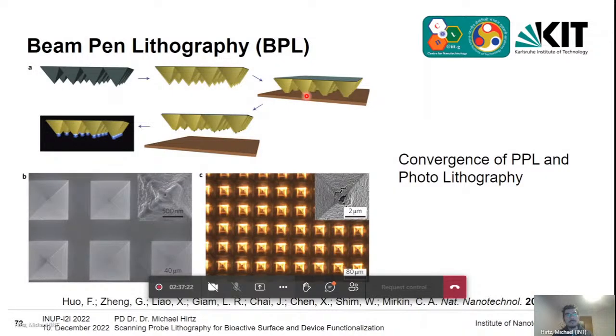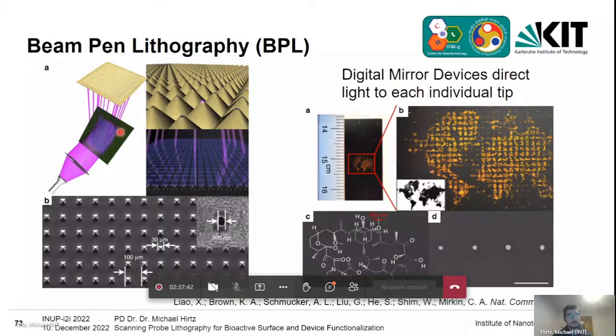The gold layer is, of course, more brittle than the polymer itself. So you can open up the small apexes of the pyramids. And this allows you, if you shine light on it, to bring a very, very confined, you can see it's even sub-wavelength confinement of the light to the surface here. And this can even be combined with so-called digital mirror devices, so DMDs.